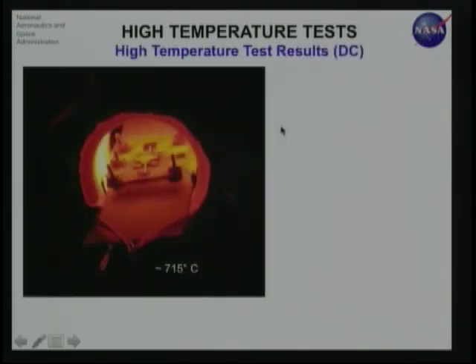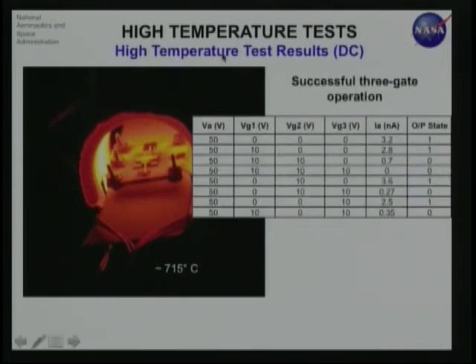After doing this, we put it inside a tantalum tungsten heater coil, and heated it to 715 degrees centigrade—that's the device on the ceramic mount that was made, and we switched the logic states at this temperature. The applied voltage at the anode is 50 volts, because that's defined by the gap—we had a larger gap in this device.